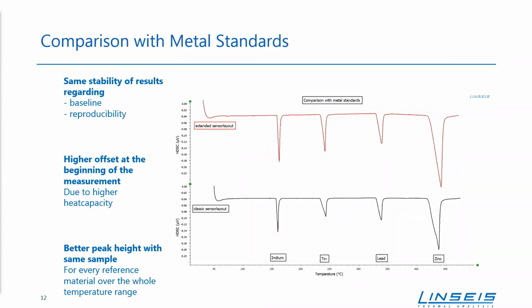But what we can see here is the higher offset on the red curve, so our new prototyped extended sensor layout. The reason for this is pretty simple. We have more material, so we have to heat up more material. So the heat capacity of our new sensor is higher. And we can see this here, the offset is bigger. And it also takes some degrees more for a perfect baseline, so we can do the evaluation maybe some degrees later in this case.